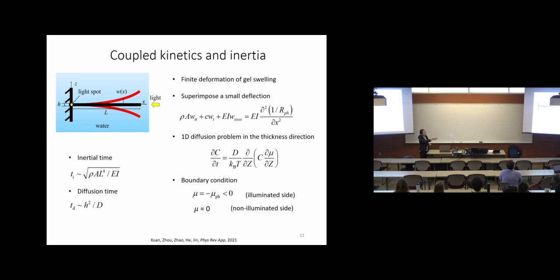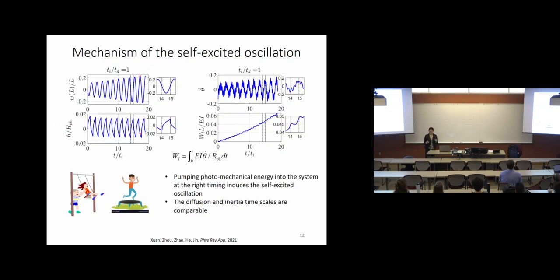In order to determine the spontaneous photo moment, we need to solve a diffusion equation across the thickness to determine the concentration gradient, and therefore we can know what the photo moment is. Combining these two equations together with the boundary conditions, on the side where you have light, the chemical potential is considered to be negative, but on the other side without light, the chemical potential is considered to be 0. Combining this equation and boundary condition, we can solve its motion. Specifically, there are multiple time scales in this problem. One time scale is the inertial time, and another time scale is the diffusion time. By solving this equation, indeed, we can observe this kind of self-excited oscillation.